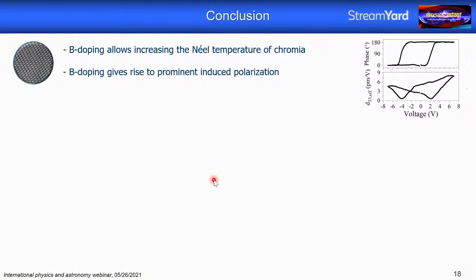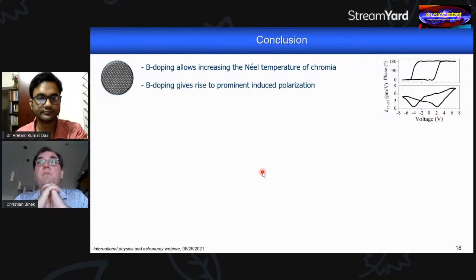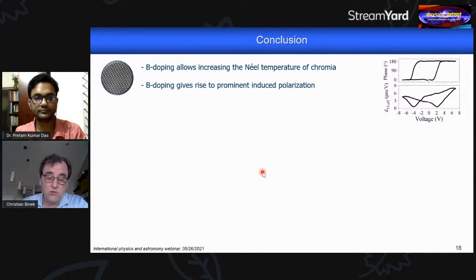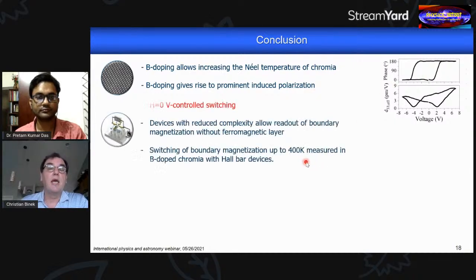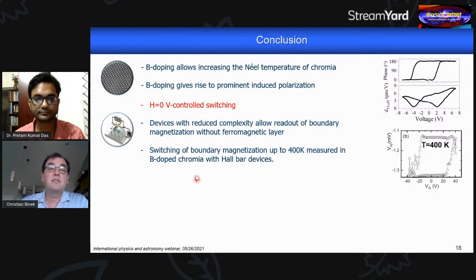Okay, with that, let me conclude. So I have shown that a boron doping of pure chromia changes many interesting properties in chromia. And not only is the Néel temperature increased, which is good, but we have effects on the anisotropy, and we also have this interesting phenomenon that this material suddenly reacts to an electric field by transient polarization, as you can see here again. And that can be used then in devices which allow us to voltage control, rotate the antiferromagnetic Néel vector by 90 degrees.